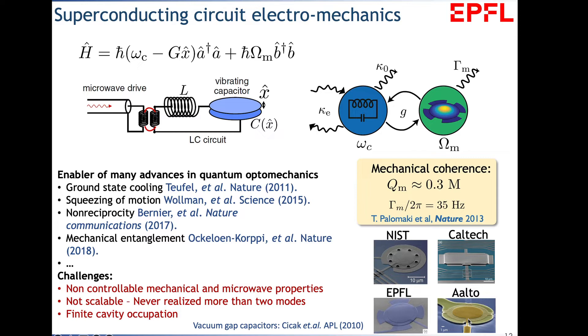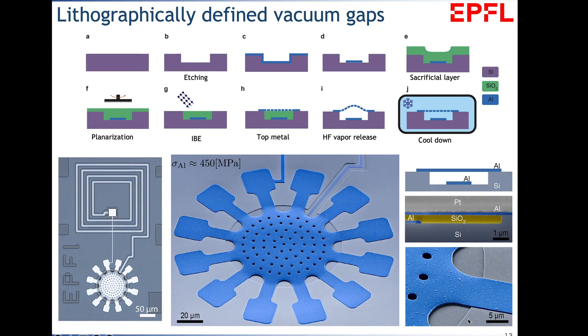We devised a new fabrication process. What we're doing is taking a substrate with a recess, depositing the bottom plate, filling with sacrificial layer, the top plate, and then releasing it. We figured that the best combination was to keep aluminum, use oxide as sacrificial layer, and silicon as substrate. The result is we have gap control—it's very precise in this system.